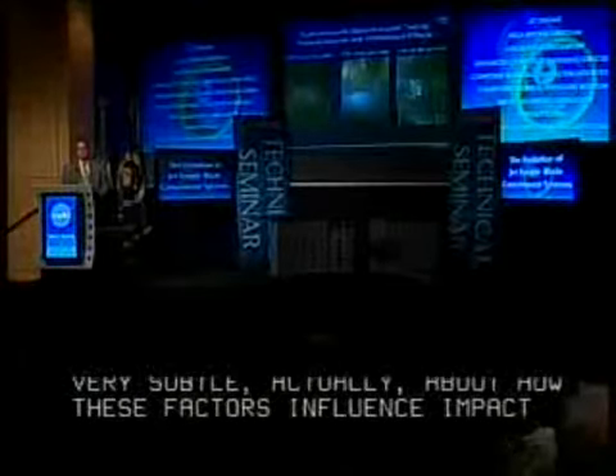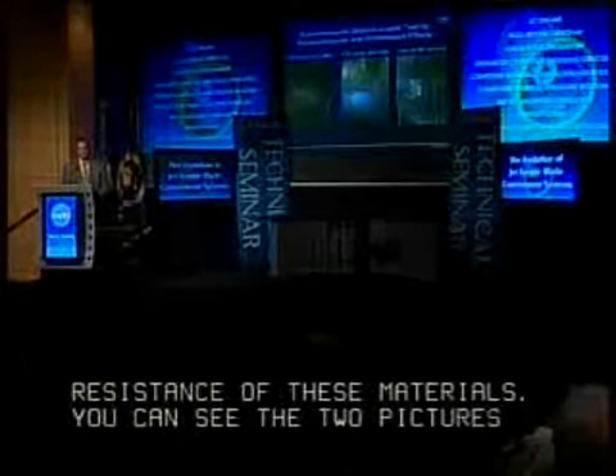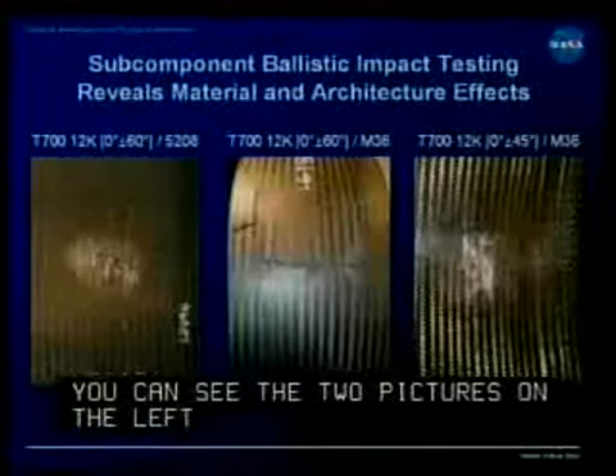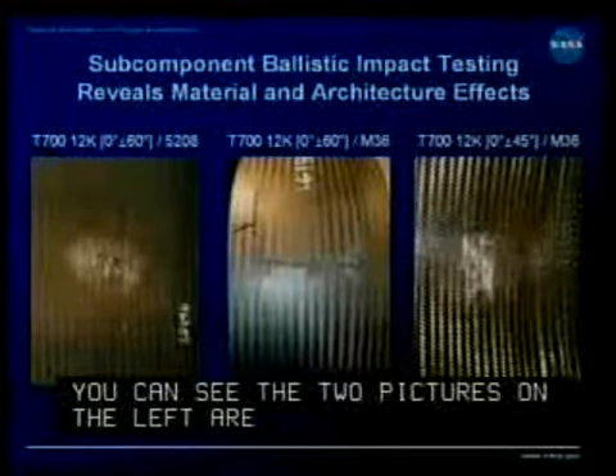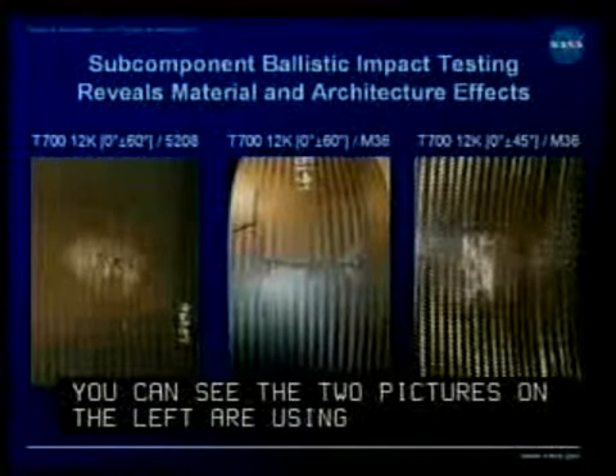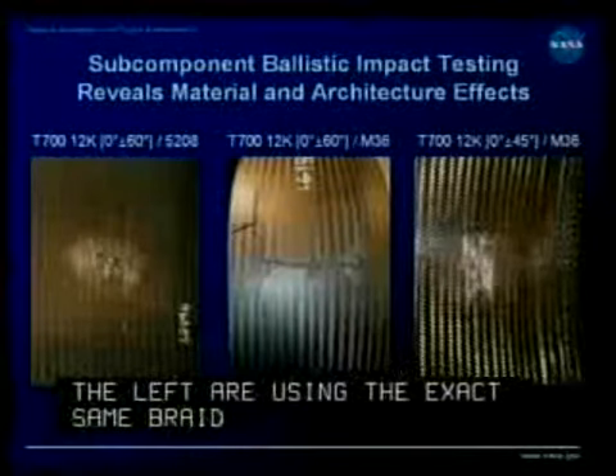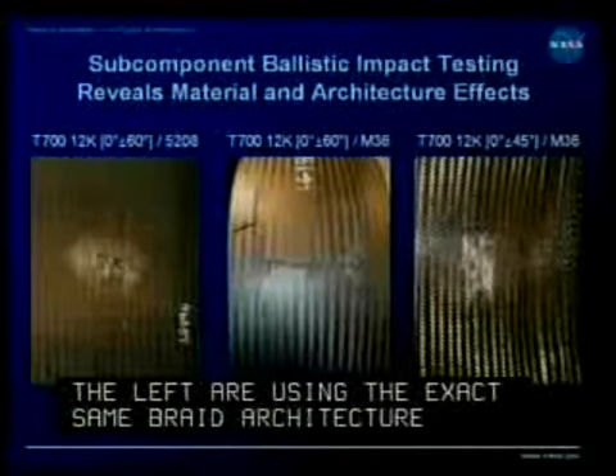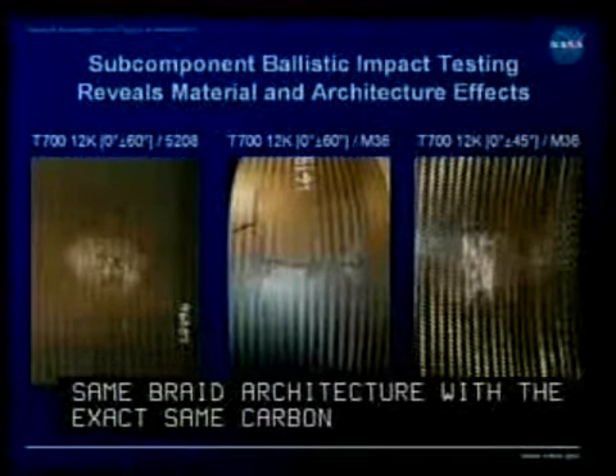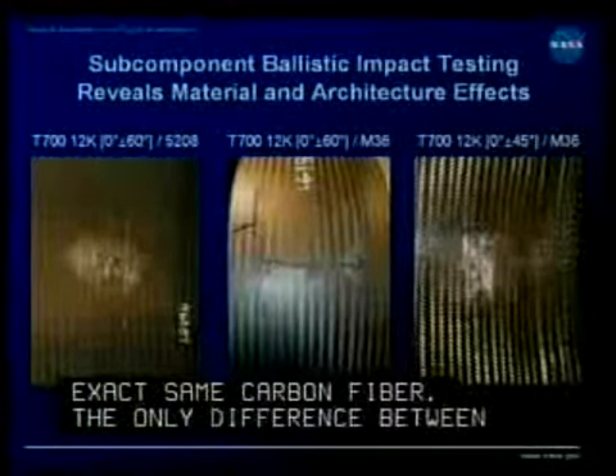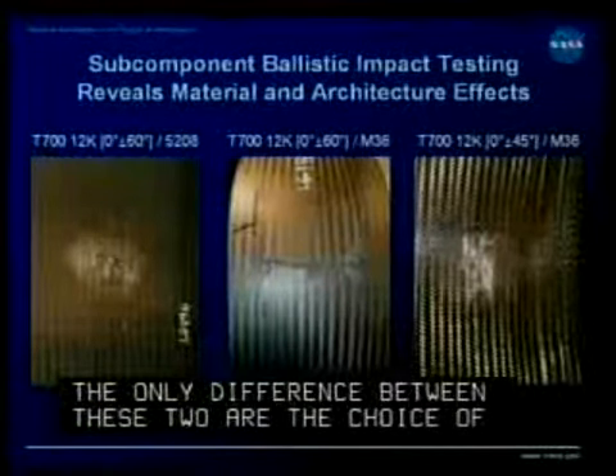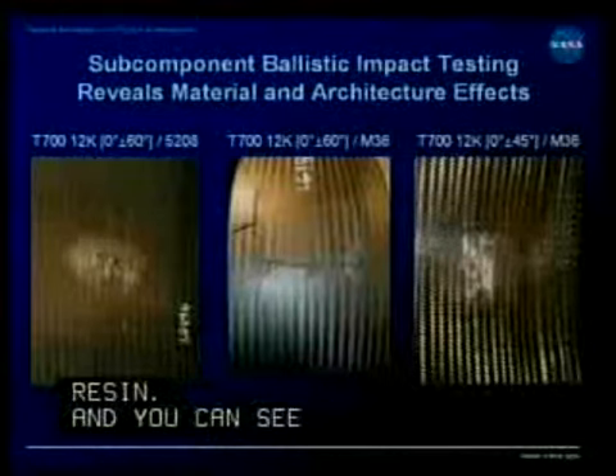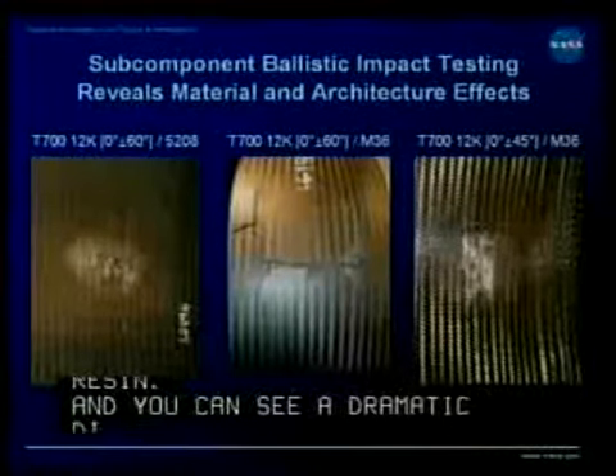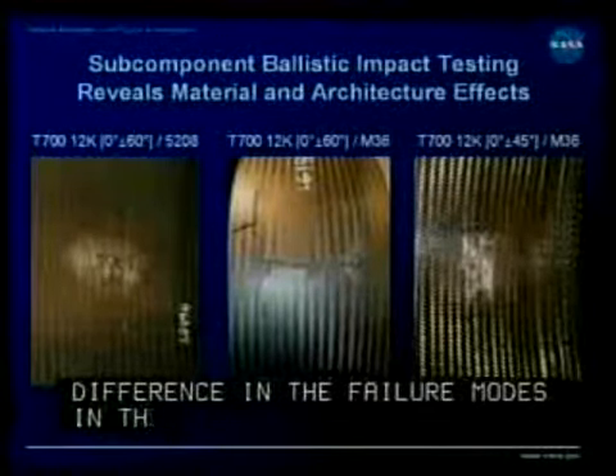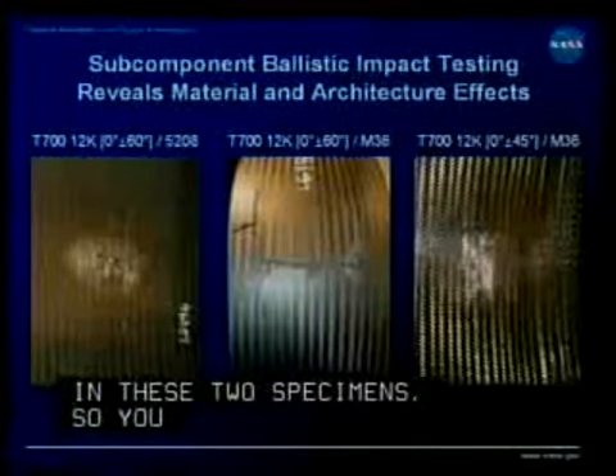You can see the two pictures on the left are using the exact same braid architecture with the exact same carbon fiber. The only difference between these two is the choice of resin. And you can see a dramatic difference in the failure modes in these two specimens. So you see just the selection of resin has a big influence on performance.